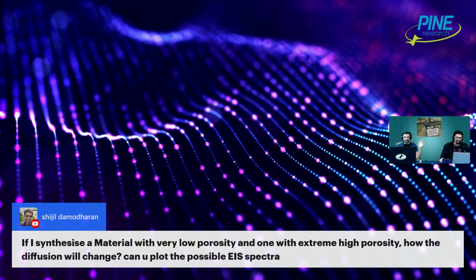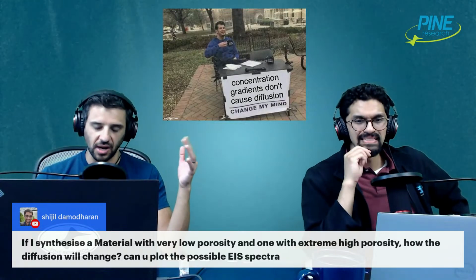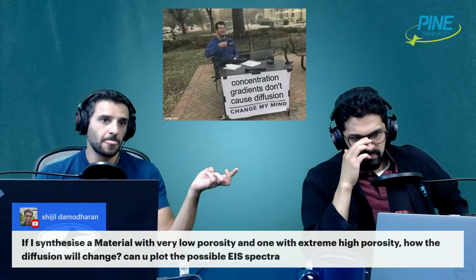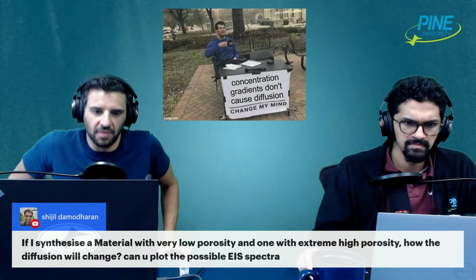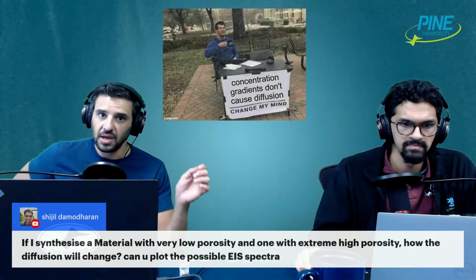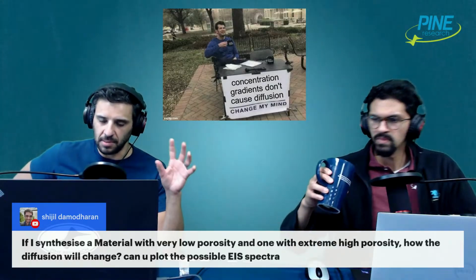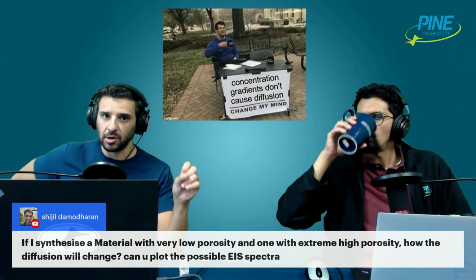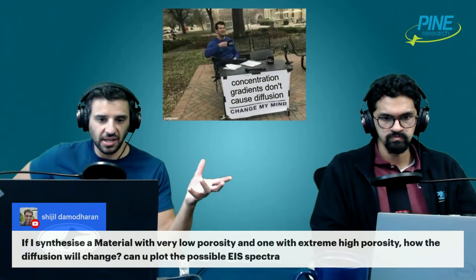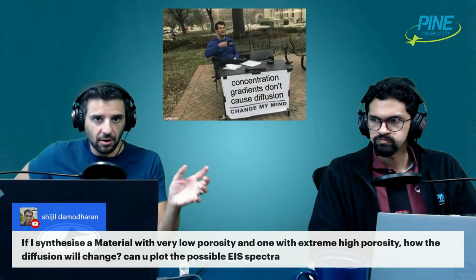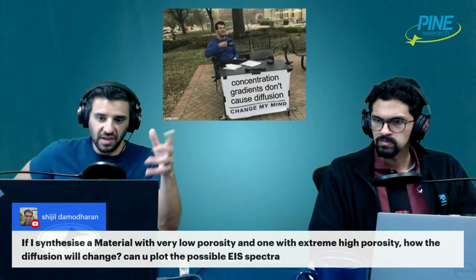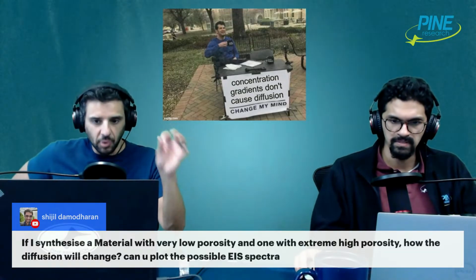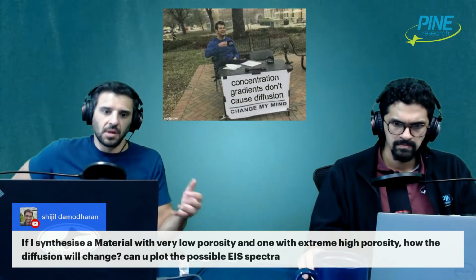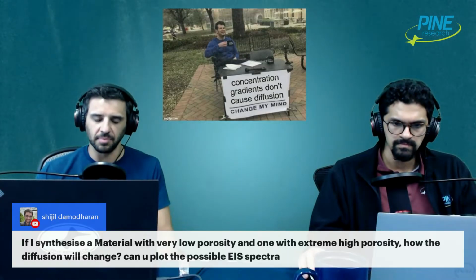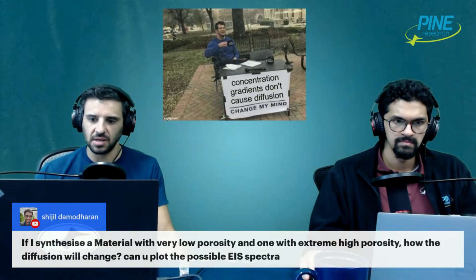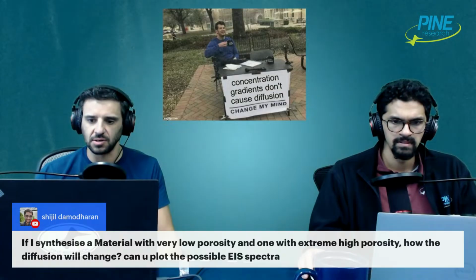We're not sure. I don't have examples of high and low porosity materials to check. There could be other things that would take effect on this. For instance, things that are working against those assumptions are the fact that smaller particles tend to have better electronic conductivity. So, while the diffusion or the Warburg impedance might be worse with low porosity, small particles, you might have better overall performance for whatever you're studying, because the small particles give you better electron transfer within the material itself. Even if the diffusion is bad within the pores, the kinetics is great. So there's more to take into account here. But as far as strictly looking at the diffusion with respect to those things, that might be what you would see. That's a good way to think it through.